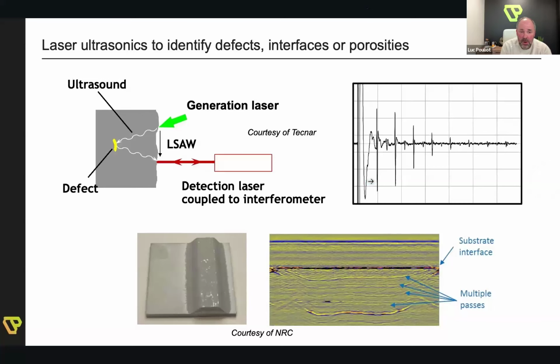So one technology we're currently integrating is based on laser ultrasonics. I won't give you a course about laser ultrasonics. We could be here for a long time, but the fundamentals are very similar to conventional ultrasound. This means we need to generate a sound wave. The big difference is what kind of hammer you use. In the case of conventional ultrasonics, you're going to use a mechanical transducer and some echo amplifying media sometimes, and you're actually going to touch the part. Here, the idea is to find a way to obtain similar information without touching the part. That way you are quite independent from part temperature, part movement, or even part geometry.